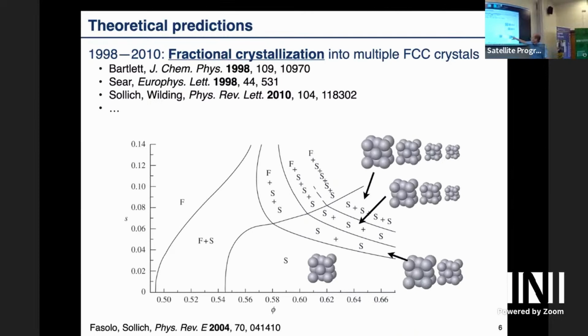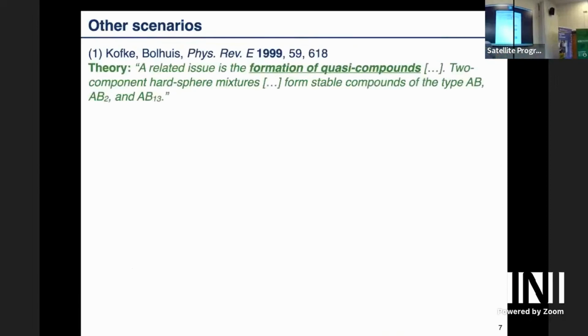So it looks like this. You have, for example, one crystal where all the large particles go, and one crystal with the smaller ones. This is called fractional crystallization. It's actually a process that's well known also in geology and in other cases. And if you look at an opal, it has a lot of different colors. Maybe you can convince yourself that's a plausible process. Then what people did here is they used density functional theory to estimate the free energies and argue that this is one process. There are also other theories. I just picked out 3.